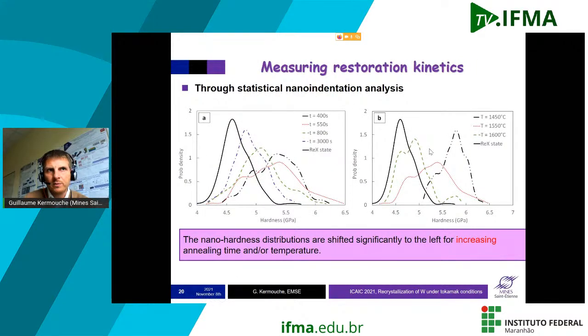So from this kind of experiment, what we can do is to measure what happened after some heat treatment. And you can see the hardness distribution that will shift from the right to the left here. So this is a consequence of recovery of materials and not recrystallization. So it happens with time or with temperature. And so clearly from that kind of measurement, we are able to measure the recovery kinetics.